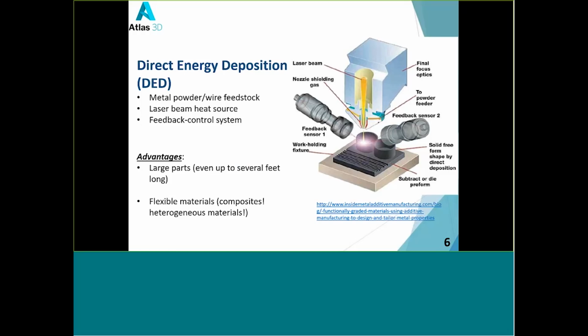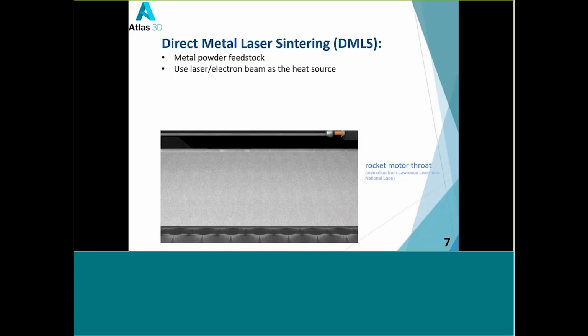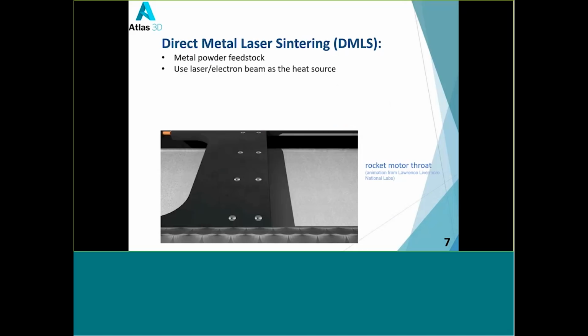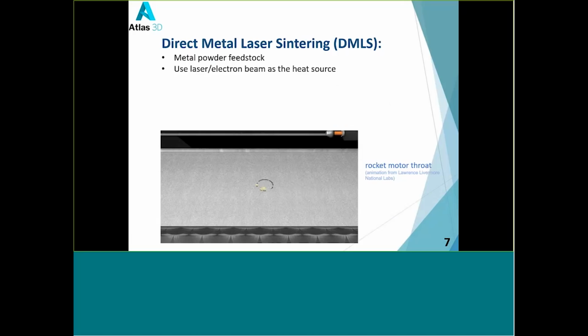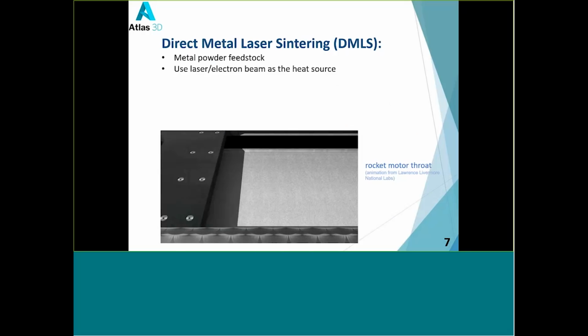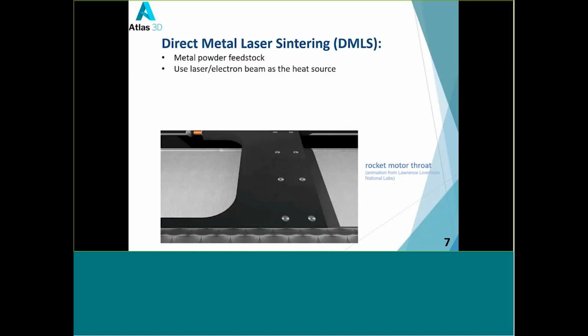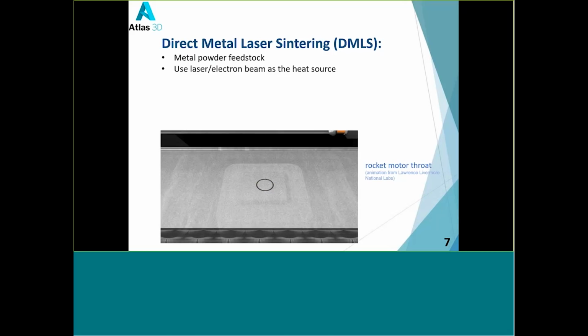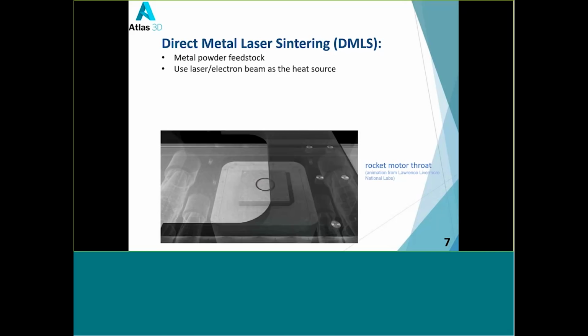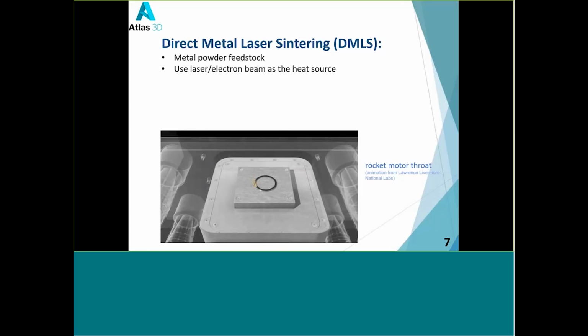And you can even change the metal powders or metal wires during the build process. The other popular metal AM process is called direct metal laser sintering process, or DMLS. Usually, metal powder is used as the feedstock, and people use laser or electron beam as a heat source. If you use laser, the part is usually built in inert gas environment. If you use electron beam, usually you need to build a part in vacuum.